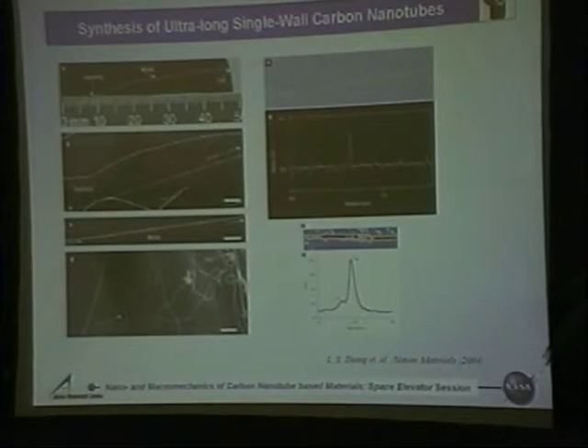If you see the top one, they show almost a 40 centimeter single wall nanotube they have grown. When I looked at it, I thought, wow, if it's such a big scale, then how can I see the nanotube? There must be some problem in there. But it's not a problem. What they did is that the data you see for that 40 centimeter long nanotube is not the real data. They created the image from that and superimposed it and just added it up. So with the naked eye you should not be able to see it.